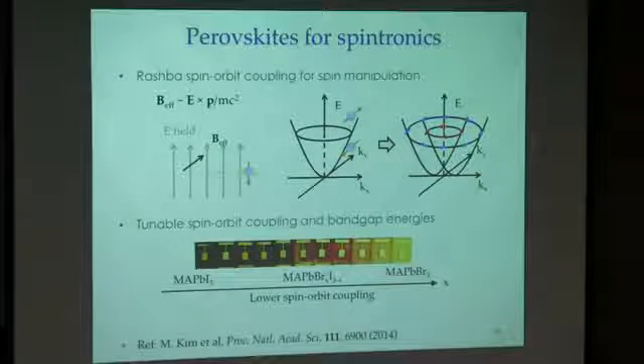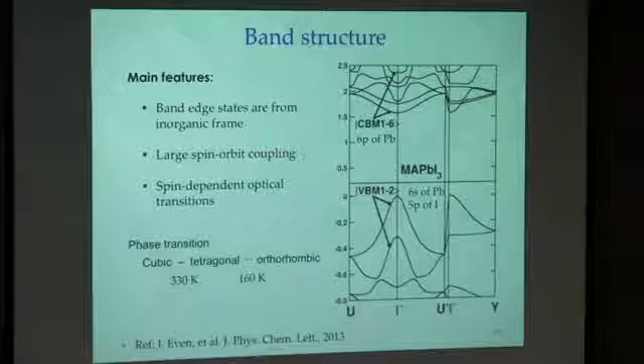To really talk about the experiment, how the technique works, we also need to look at the band structure. This shows a band structure from first principle calculations. I'll just mention three main features. First, the band edge states are from the inorganic frame. For example, the conduction bands are p orbitals of lead, and the valence bands are 6s of lead and p orbital of iodide; it's their hybridization. There is very large spin-orbit coupling in the conduction bands. And because of the symmetry of the bands, we have spin-dependent optical transitions.